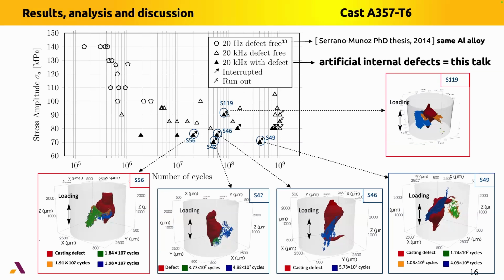The other important point is that all the symbols with an arrow correspond to cracks which are initiated in the specimen, but the specimen are not broken. So it means we know the history of the crack initiation and growth up to this point, for instance, here, up to approximately 2 to the 7 cycles. We obtain this image of the internal defects with the crack. We know the evolution of the crack after different number of cycles, but the specimen integrity is still good. It is not broken. So today, I'm presenting the results on 2 specimens, the specimen 119 and the specimen 56.